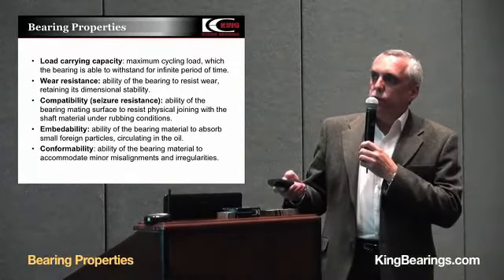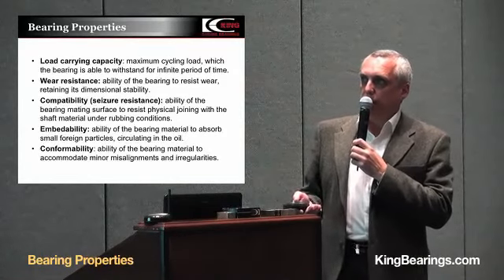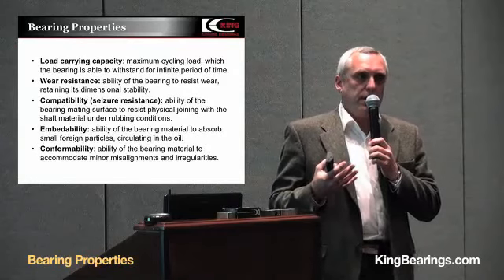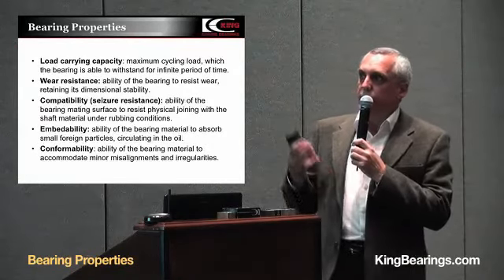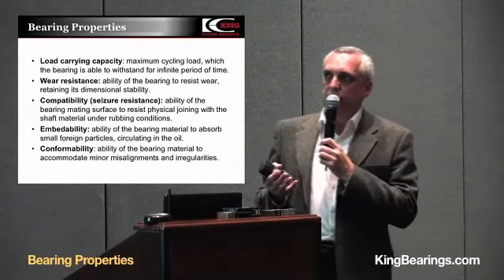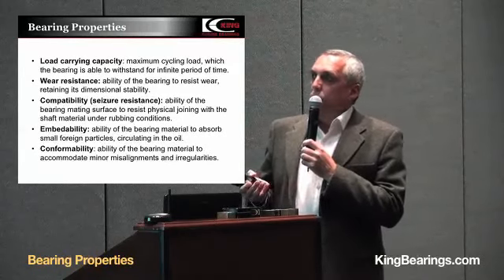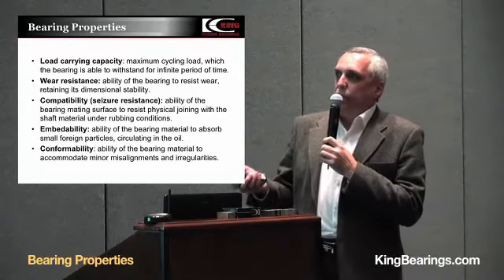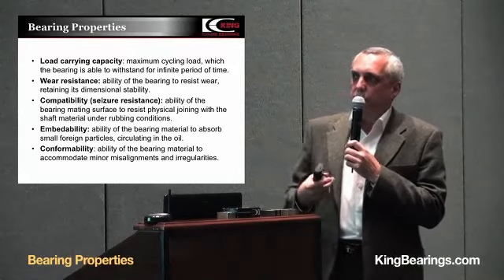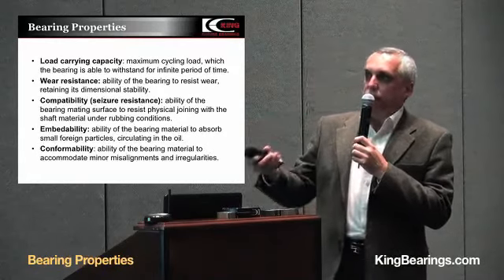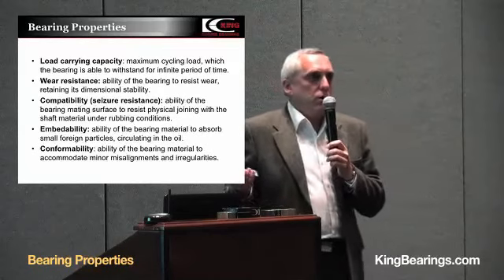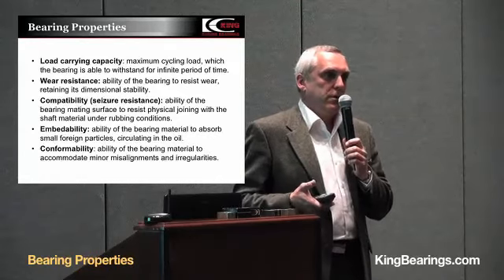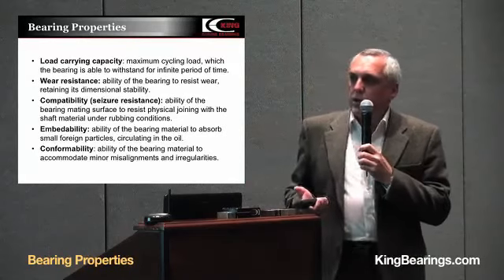If you look at these properties, you see that the first two — load carrying capacity and wear resistance — attribute to the strength of the bearing material. The harder and stronger the material, the better: the higher its load carrying capacity and the higher its wear resistance. The three last properties are soft properties. Compatibility, embeddability — the softer the material, the better it absorbs small foreign particles — and conformability. So what we have? We need a material that is hard and soft. It's a paradox, yes, it's absurd, but it is possible.